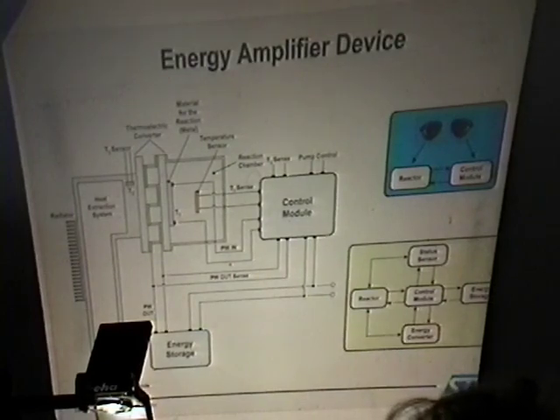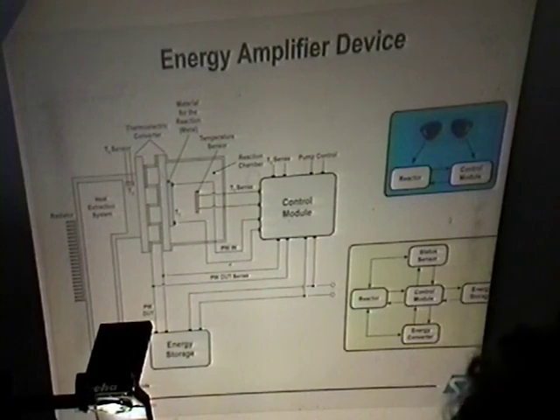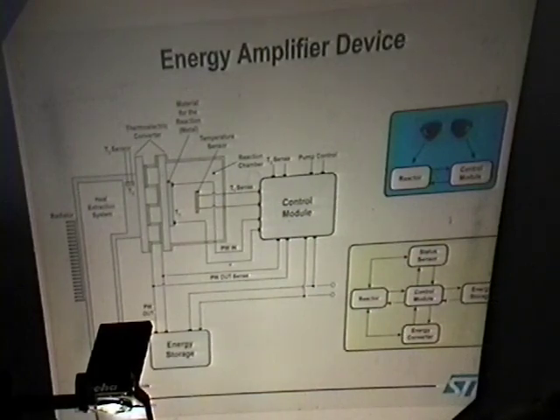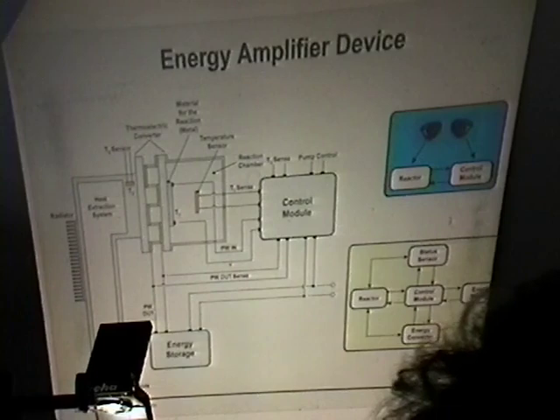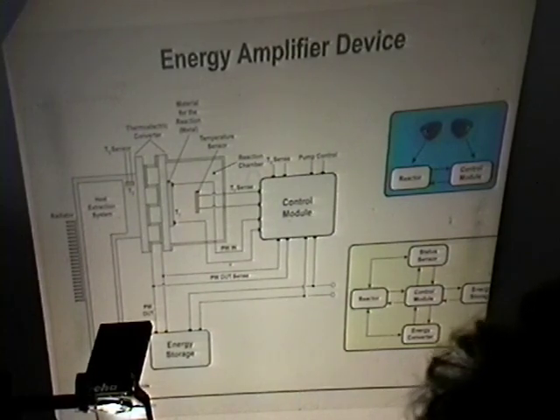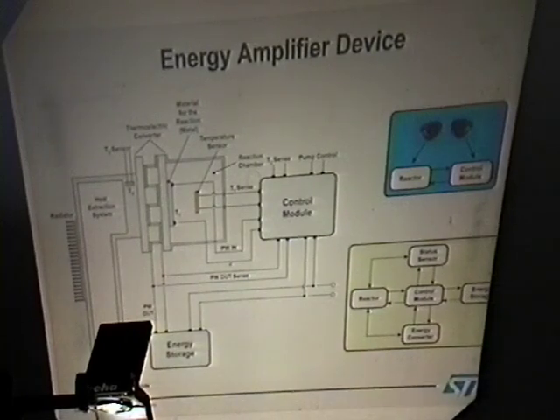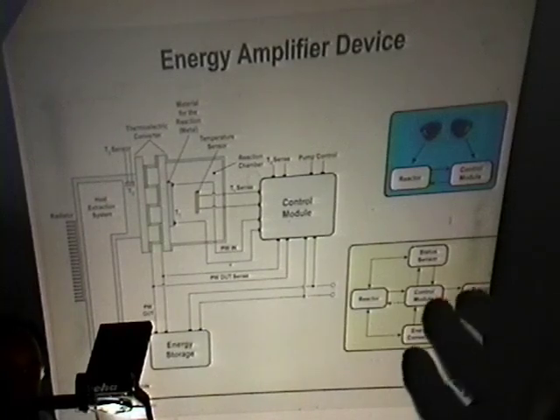First of all, we need to test the material, the core of the system, the reactive material. The material for the reaction, in our case, is a thin film of metal, and I would like to use nickel as long as I can. I prepared also experiments using palladium. We need a temperature sensor just to measure the excess, the temperature rising when something occurs in the metal lattice. For the final device, obviously, we need some thermoelectric converter to get the energy coming from the reaction to the energy storage system and to deliver the energy to some other device.